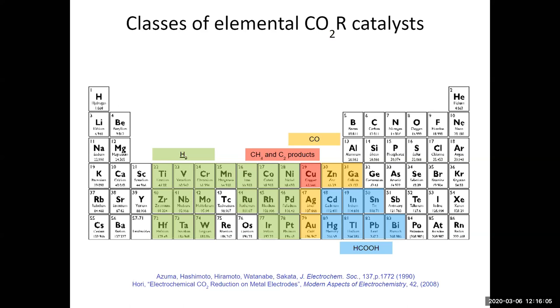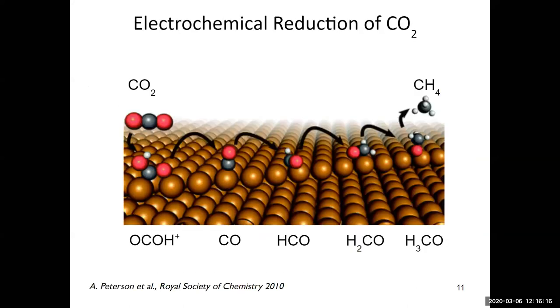And an obvious place to start is to say, what is special about copper? And could we find other things that are not copper, like some alloy that might have interesting properties? So people have already studied CO2 reduction on copper surfaces. This is CO2 reduction on a step going to methane, a very simple pathway. Make CO2, hydrogenate again, and you lose water, hydrogenate, eventually you get methane off.